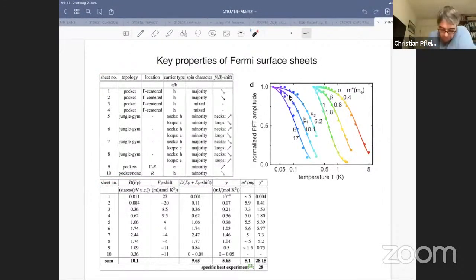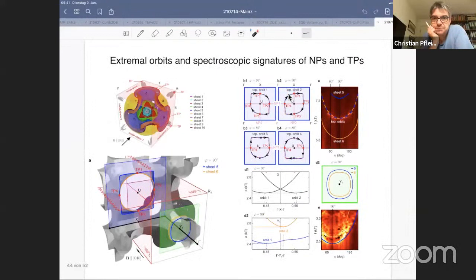And here's actually now a list also looking into the density of states and the contributions due to the specific heat. We can compare this with the effective masses that we get out of the temperature dependence of the oscillation amplitude. And it turns out actually that the sums add up. So we see all of the Fermi surface sheets there. Everything matches very nicely. This is basically also the origin of saying that the quasi-particles in this type of spin polarized Landau Fermi liquid are dressed with strong spin fluctuations. So all of this is consistent. Here's now the main argument where we see that the nodal planes play a very important role, and that in the direction of the magnetic field, the nodal planes no longer exist.